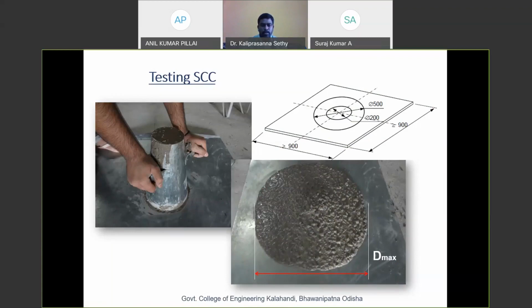Here is the apparatus, the slump flow apparatus. You can see this is the plate which has markings of 200 and 500 mm diameter. We have to keep our slump cone like this and fill the cone with the concrete. Once we remove the cone, immediately we have to take a reading of the duration for the concrete to reach D500, meaning this diameter. At the same time we have to take the reading of the maximum diameter the concrete reaches. From that we can check the fresh property of the concrete developed as per the criteria given by the EFNARC guidelines.